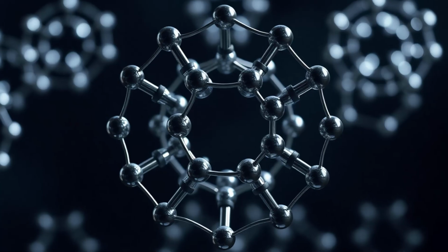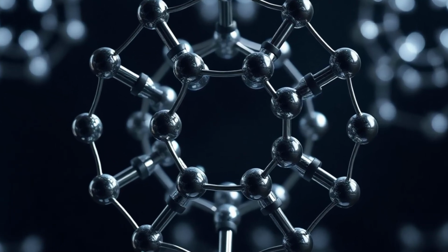And their specific insight was to focus on something called the ring current effect. Okay, imagine the carbon atoms form these hexagonal rings, like little bits of graphene. When ions squeeze into the pores, the electrons in these rings, the pi electrons, start circulating because of the NMR's magnetic field. This circulation creates its own tiny magnetic field, and that causes a distinct shift in the NMR signal we detect. The shift, they quantify it precisely as the A value, and that value becomes the key indicator, the molecular fingerprint, if you like.